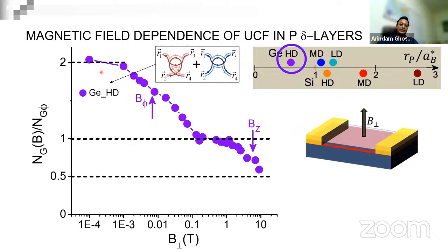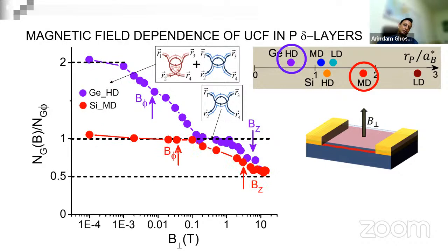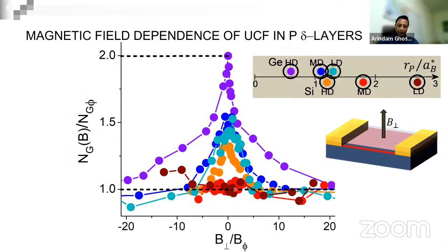But if I go to a strong interaction regime, then the noise is missing the first reduction. That means even if I apply a magnetic field, there is no factor of 2 reduction, very similar to what you see in the onset of magnetism. It shows that at very strong interaction, randomly doped two-dimensional semiconductor probably becomes magnetic themselves. And this is something we saw earlier as well. As you increase the interaction, you can see there is no factor of 2 reduction.